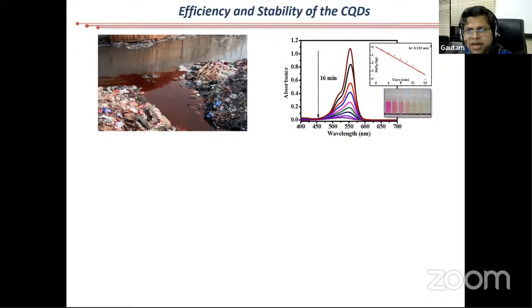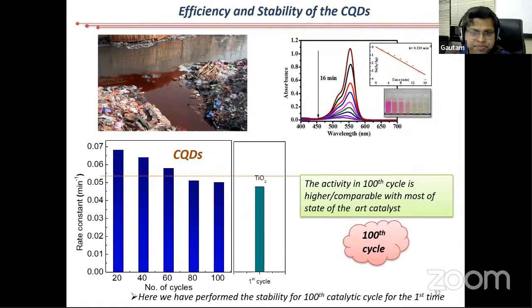Now, one of the applications, I showed you this picture that we want to degrade these dyes. You can see this is a colored dye. On the right hand side, these colored bottles, you can see this actually degrades with light. If you take a pinch of carbon dots, it degrades and the color goes away. Many catalysts are known for this. As I told you, for say 50 years, people have developed this kind of catalyst. But it is very interesting because it is very stable.